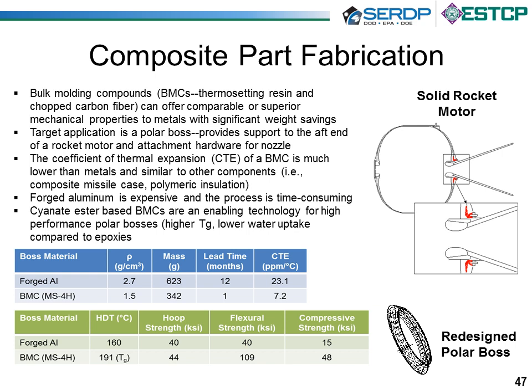Anyway, it's essentially used to provide support to the aft end of a rocket motor and attach the nozzle to the missile case. These are typically produced from aluminum, and we believe that by producing it from a bulk molding compound, we could both reduce the weight and reduce the lead time for fabrication for these materials. In addition, the properties, for example, the flexural strength and compressive strength of bulk molding compounds can actually outperform aluminum.